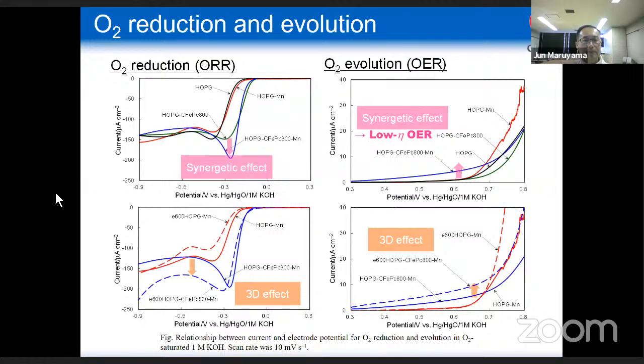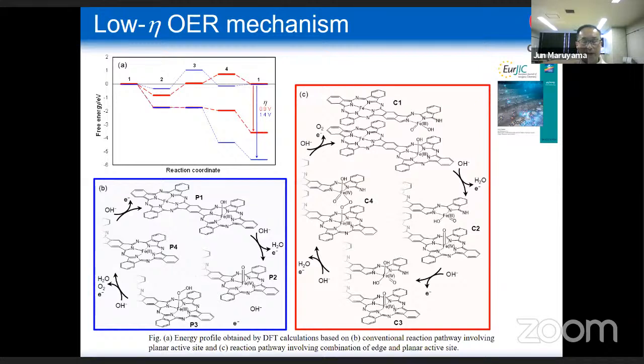And this is results for a catalyst for oxygen reduction activities and oxygen evolution activities. One of the most outstanding results here is the finding that these surfaces can be very active from very low overpotentials. And these very low overpotentials can be achieved considering these reaction mechanisms involving two kinds of active site.